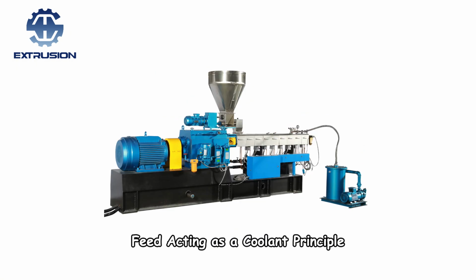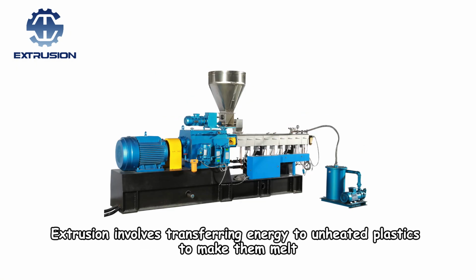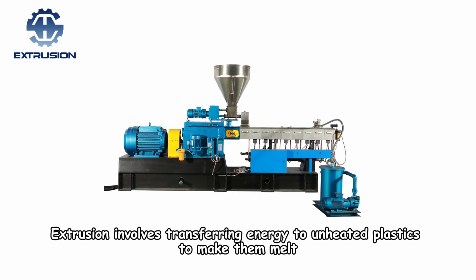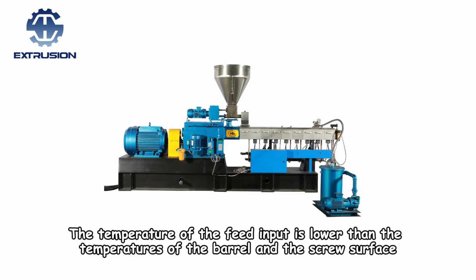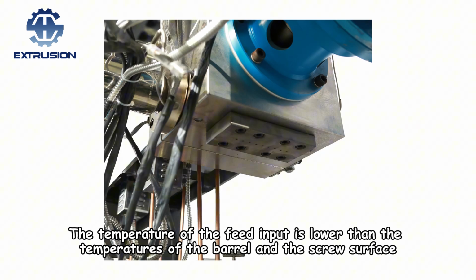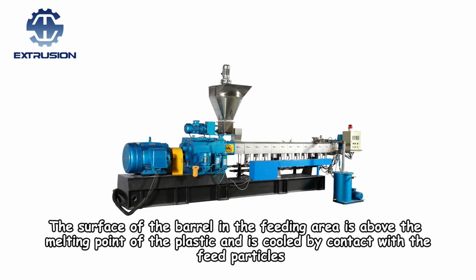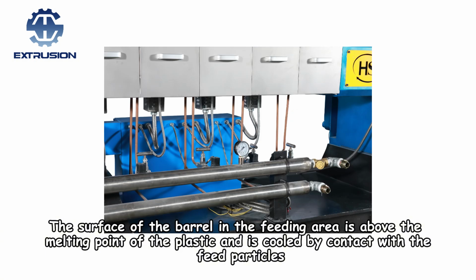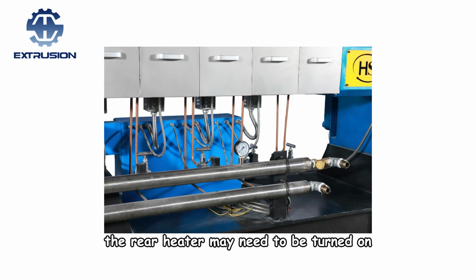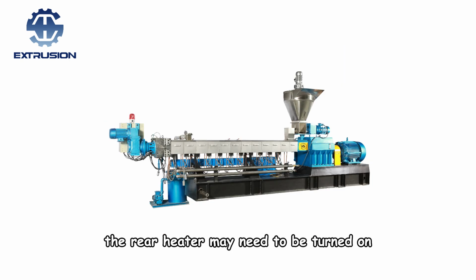4. Feed acting as a coolant principle. Extrusion involves transferring energy to unheated plastics to make them melt. The temperature of the feed input is lower than the temperatures of the barrel and the screw surface. The surface of the barrel in the feeding area is above the melting point of the plastic and is cooled by contact with the feed particles. If necessary, the rear heater may need to be turned on.